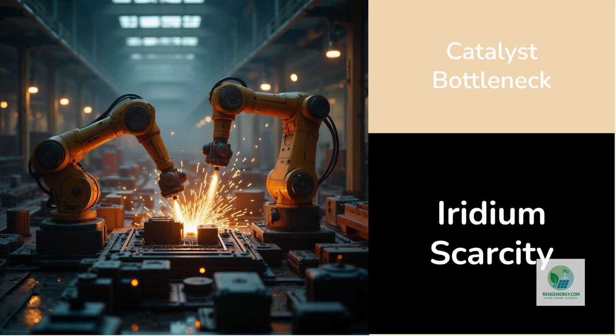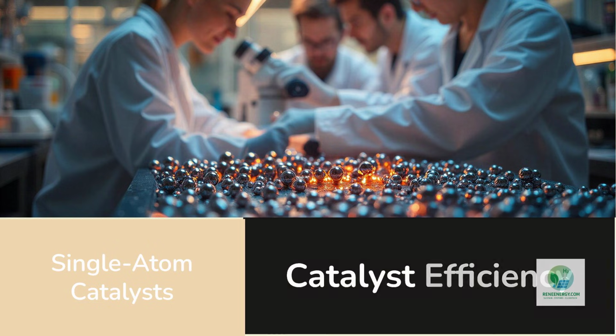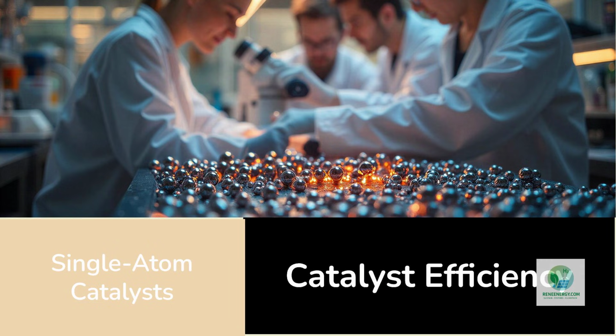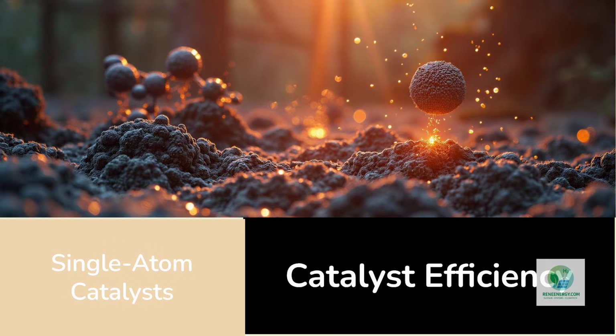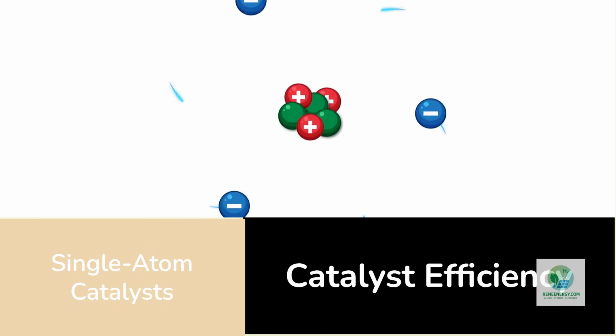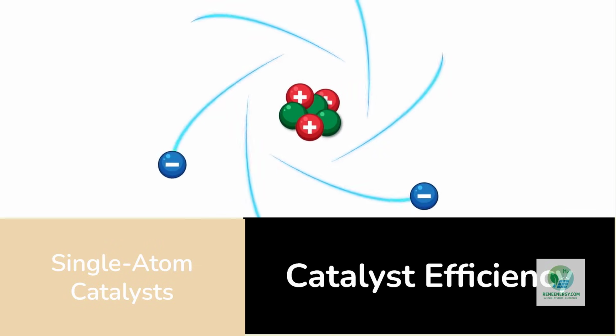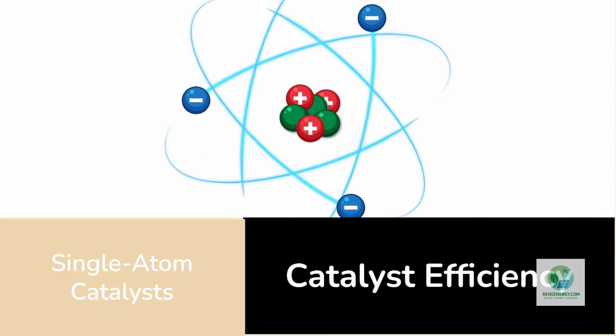But the Materials 4.0 revolution is breaking this bottleneck decisively. At ETH Zürich, researchers created single-atom catalysts where individual metal atoms, iridium, platinum, nickel, or cobalt, are anchored to nitrogen-doped carbon supports. Traditional nanoparticles have only a fraction of their atoms exposed. Most are buried inside and do nothing. Single-atom catalysts solve this. Every atom is active. That means the same catalytic performance with 95 to 99% less iridium.